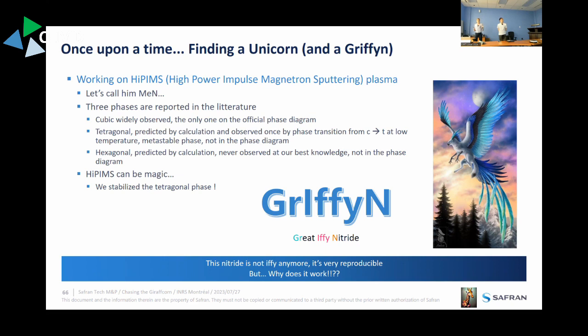The last one is the hexagonal one that is predicted by calculation, never observed from what we know, and also not in the phase diagram. Where I can say I do magic every day and I'm very proud of it is that we observed the tetragonal phase, but we stabilized it. So right now, using HiPIMS, we are able to deposit thin films of this material in tetragonal phase, stable. It doesn't move at all. You can do whatever you want, it works. So at the early beginning of the project, we called him the great Iffy nitride. But as you can see, this is not iffy anymore.